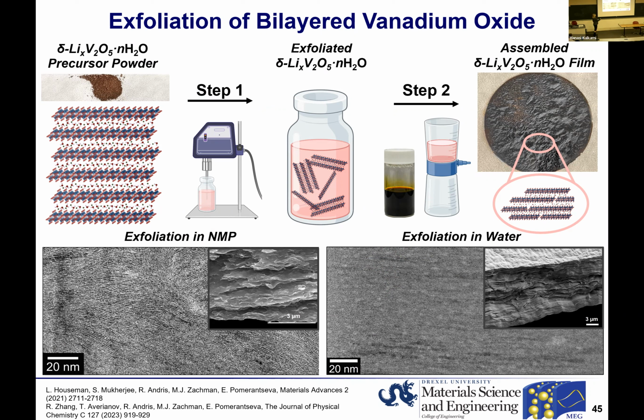And to our surprise, when we filtered the obtained suspension, we got a freestanding film with a very different color compared to the precursor. The precursor is reddish brownish, and the film that was produced simply after sonication is shiny black. The scanning transmission electron microscopy characterization done by Dr. Michael Zachman at Oak Ridge National Laboratory showed us that depending on the solvent that we use during the sonication process, the structure of the final freestanding film is very different.